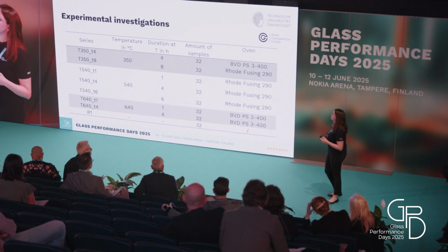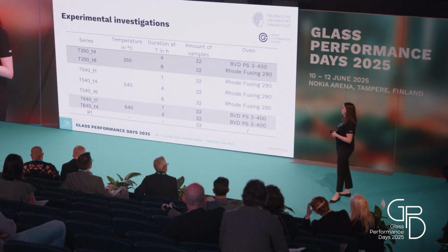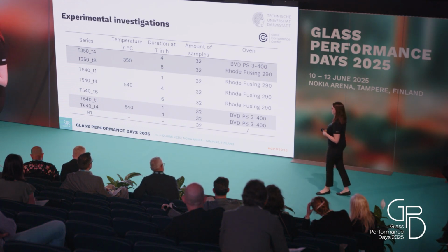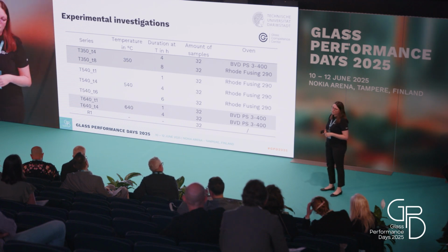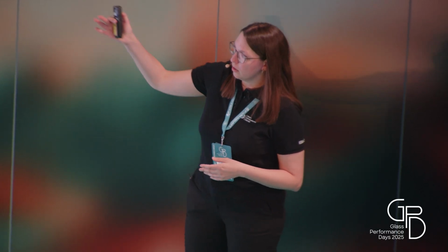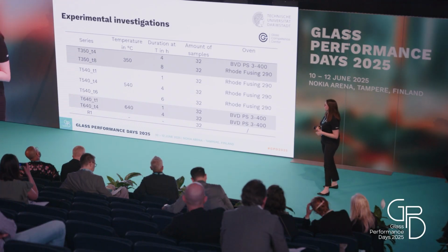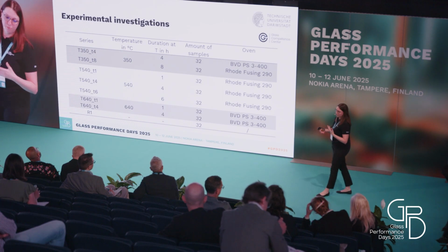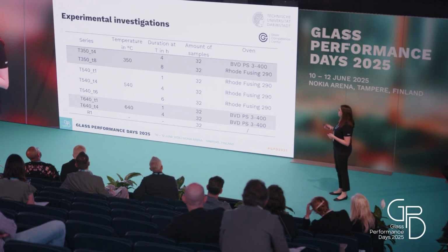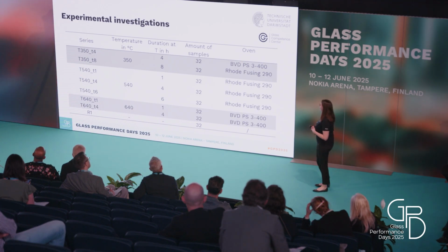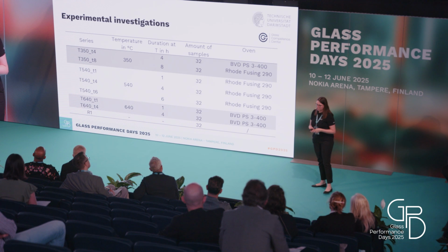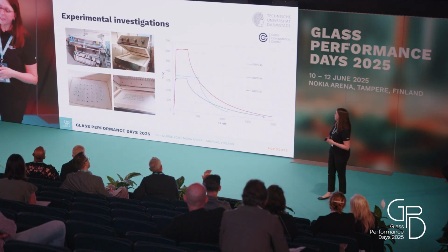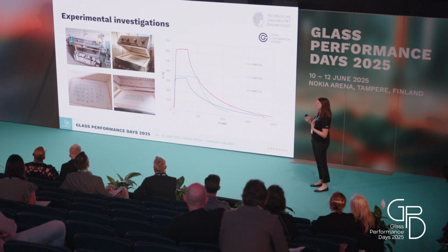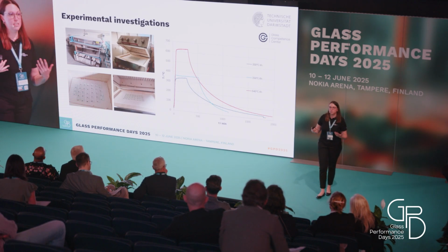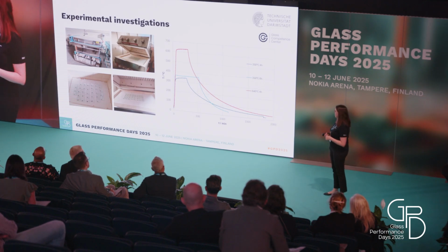We have investigated 3 different temperatures. The lowest was 350 degrees Celsius. Then we had one with 540 degrees Celsius and one with 640 degrees Celsius. And the duration of the treatment also varied between 1 and 8 hours, and for all 3 temperatures, we also investigated a 4-hour treatment just to better compare the results afterwards. For each series, we had 32 samples, and we used 2 different ovens for our investigations just due to time issues. Here we see the 2 ovens, and what was important for us was that one series was treated at once, so we had each time 32 samples in the oven.